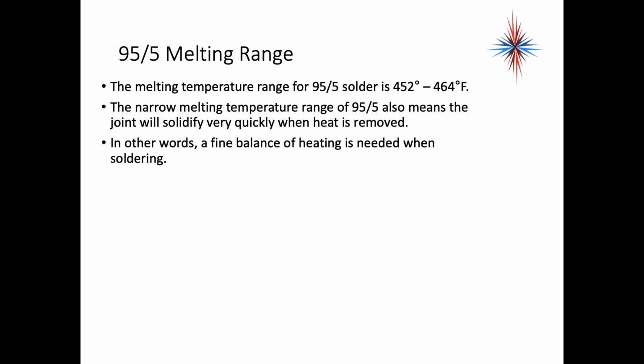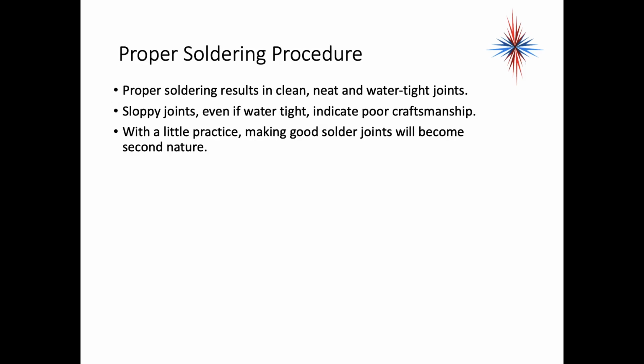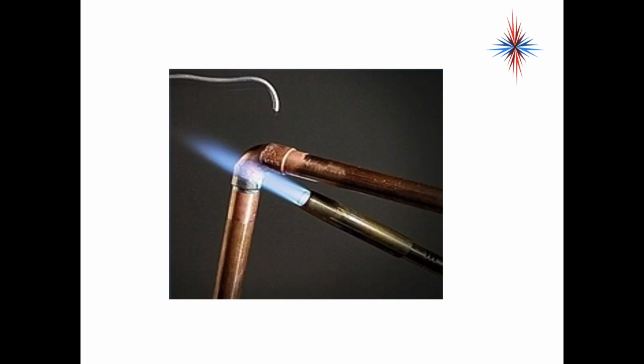The melting range for 95-5 solder is about 452 degrees to 464 degrees. This narrow melting range also means that the joint will solidify very quickly when the heat is removed. In other words, there's a fine balance of heating needed when soldering. Proper soldering results in very clean, neat, and watertight joints. Sloppy joints, even if they're watertight, are indicators of poor craftsmanship. With a little practice, making good solder joints will become second nature. This is an example of someone soldering.